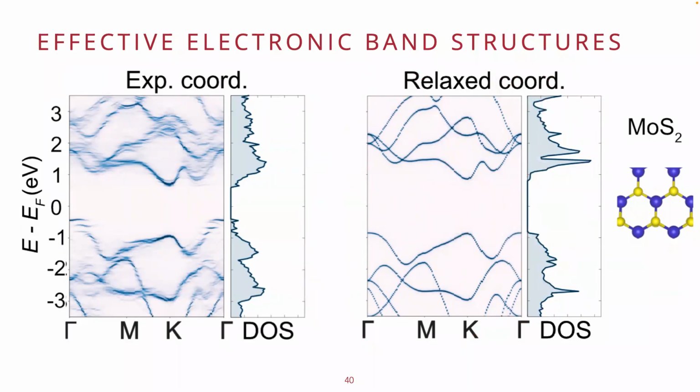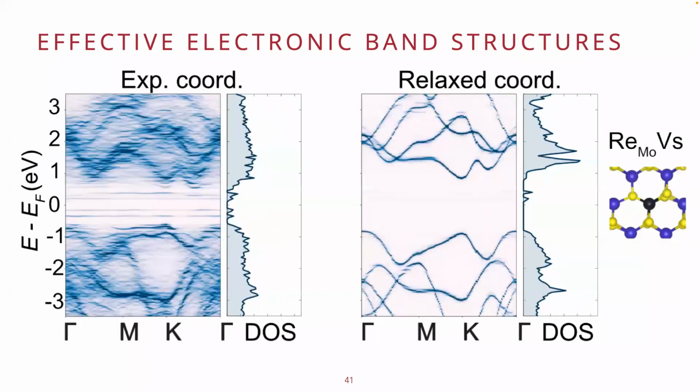And you can actually see that here. Due to the fact that we have experimental strain, you're seeing a lot of shadow bands and a distortion of our electronic band structures, and even a change from a direct to indirect band gap that you wouldn't really expect. Now, if we choose areas with rhenium dopants, we get something even more interesting, right?